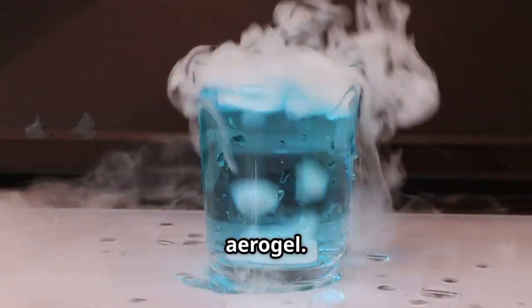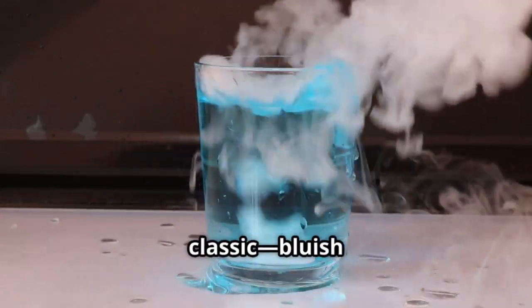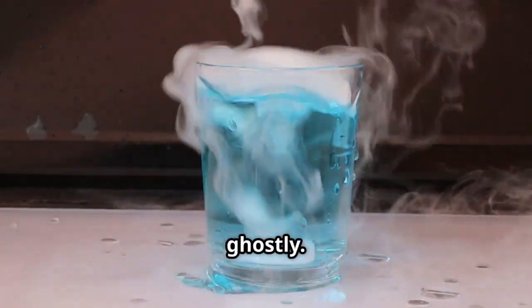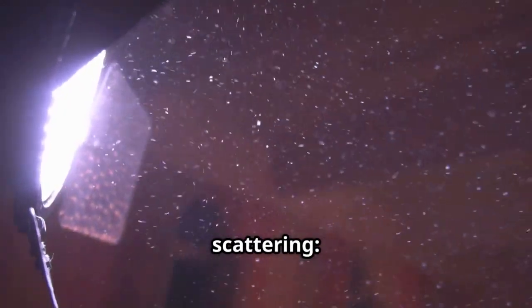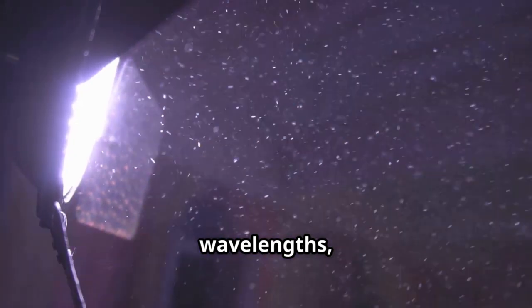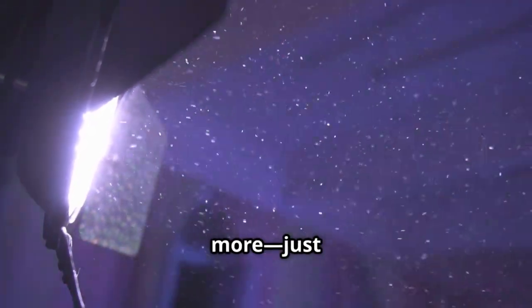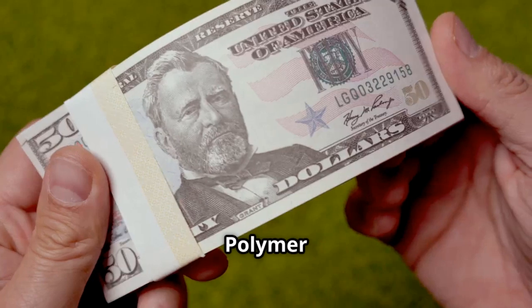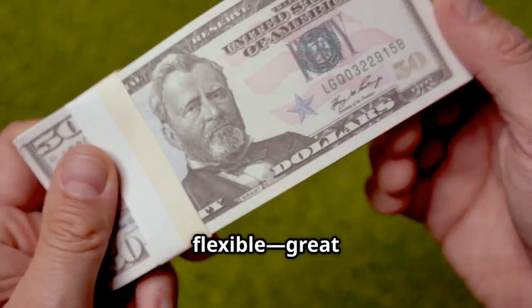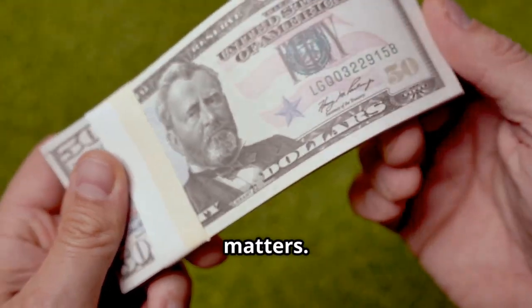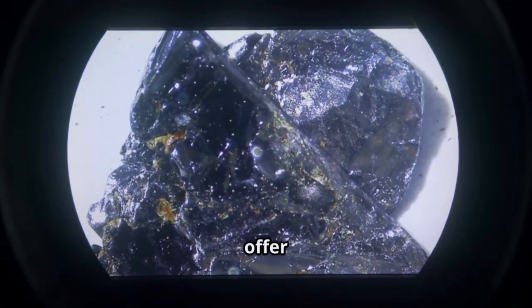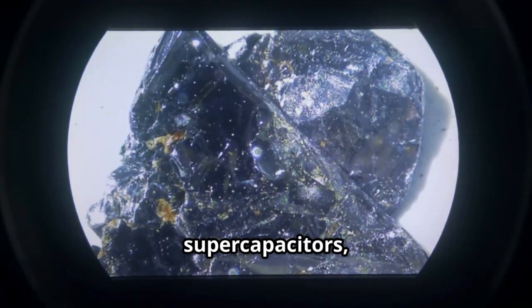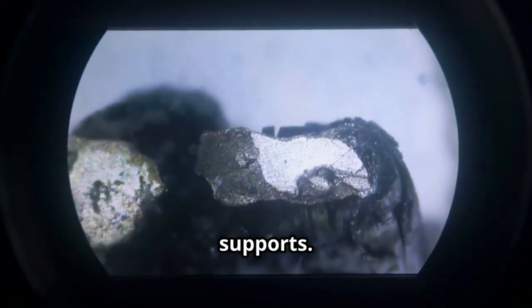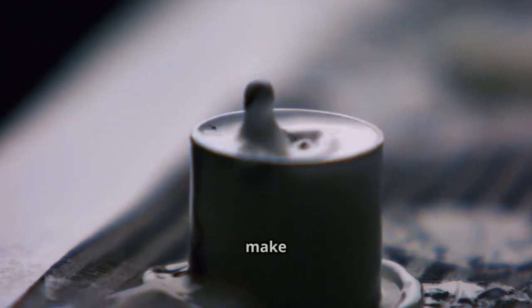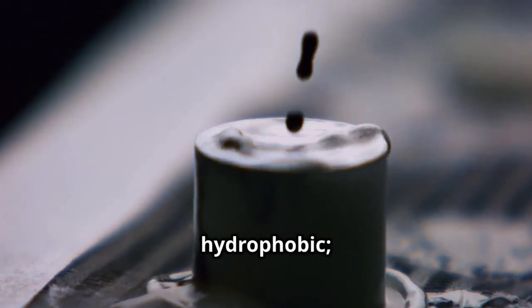There isn't just one aerogel. Silica aerogel is the classic, bluish and ghostly. That blue tint comes from Rayleigh scattering. The pores are smaller than visible wavelengths, so shorter blue light scatters more, just like the sky. Polymer aerogels can be tougher and slightly flexible, great when impact resistance matters. Carbon aerogels conduct electricity and offer huge surface area for supercapacitors, electrodes, and catalyst supports. Chemists also add silyl groups to make silica aerogels hydrophobic. Untreated ones can absorb moisture and lose performance.